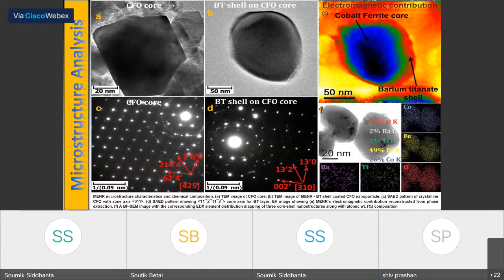So this is the core cobalt ferrite. It is coated with barium titanate using the Pechini method. And then using the selected area electron diffraction pattern, we can see the cobalt ferrite single crystallinity, as well as the barium titanate shell is also single crystalline in nature. This is one of the best outcomes from this project, because I will explain in the later slides also.